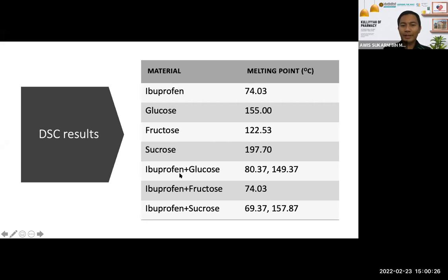When we combine the ibuprofen and the glucose, you can see the ibuprofen melting point shifted up a bit to 80 degrees, and the glucose shifted down a bit to 149. For the fructose, the melting point of the ibuprofen is basically similar, but we cannot see the melting point of the fructose. At this point, we speculate that when mixed with the ibuprofen, the melting point becomes too small for it to be detected.